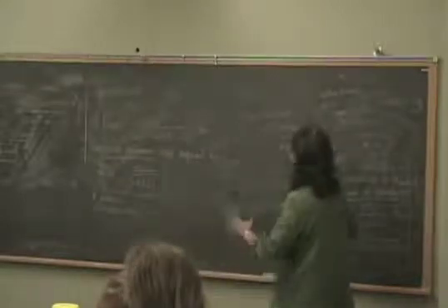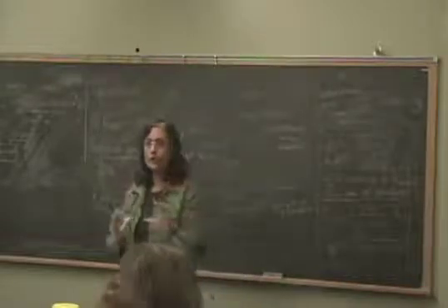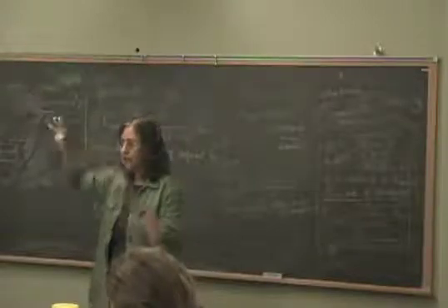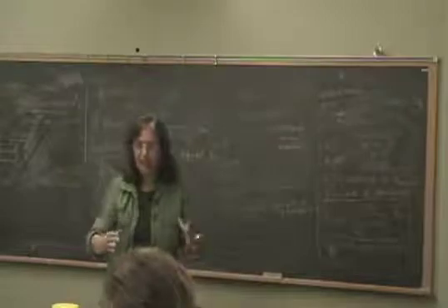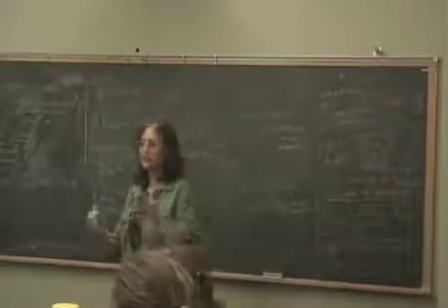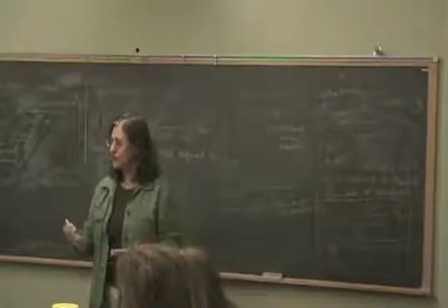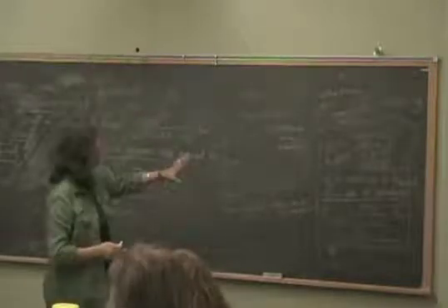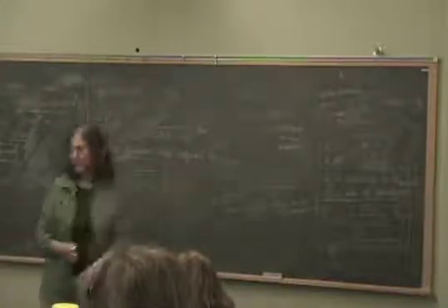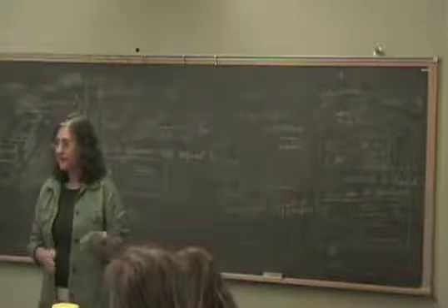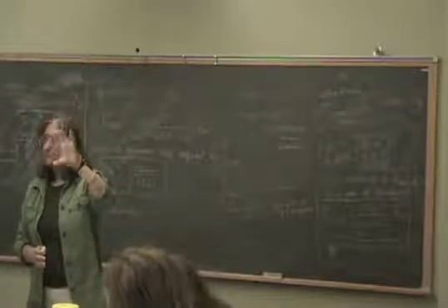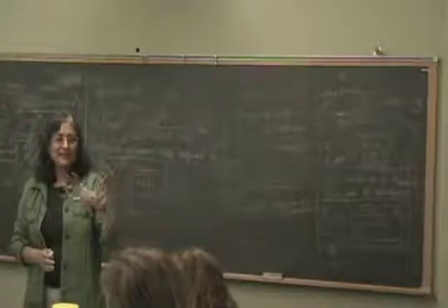Now, what we have seen is we started out with a gold plasma frequency of the bulk, which was way in the ultraviolet. By putting in the size effect and the dielectric effect, it has come into the visible range, not quite at 500 nanometers, but at 600. What is missing is the fact that gold also has a dielectric constant correction because of the interband transitions. I'm going to show you some real data there, because while we can understand the color of the dot through surface plasmons, we cannot understand the color of gold.